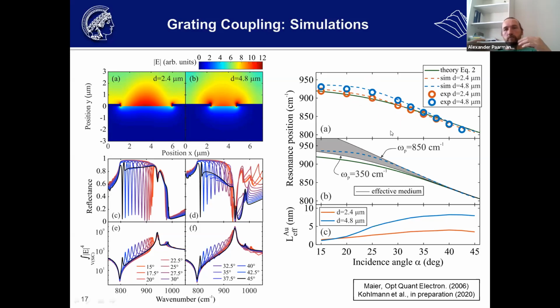And we're trying to rationalize this in some way, and my simple-minded view was, well, maybe we could just think that there is some hybridization, that you do some localized plasmon excitation in the gold with the free carriers in the gold, alongside the mode that you excite in the silicon carbide just from the electric field, so that you get some hybridized modes in this case. I was trying to see if you have that. If you have some plasmonic contribution, that would lead to a blue shift of the dispersion.